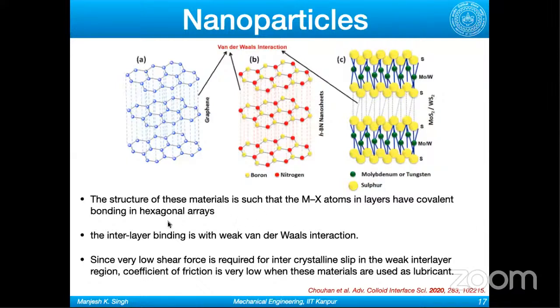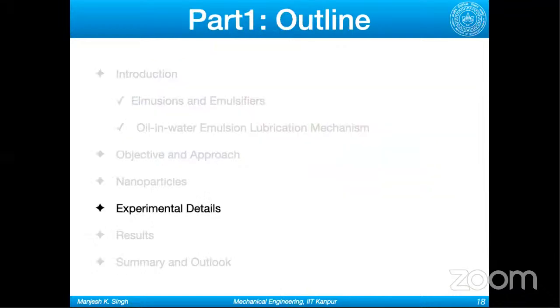because of the covalent bonds, they can support the normal load, but because the interlayer binding is very weak, due to the van der Waals interaction, when you apply shear, they shear easily. That's why you have very low friction. So the idea was that we just replace oil with these nanoparticles, which can shear easily and will give us low friction, or low coefficient of friction, so to say.